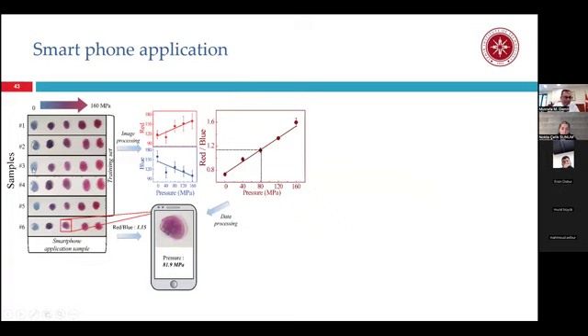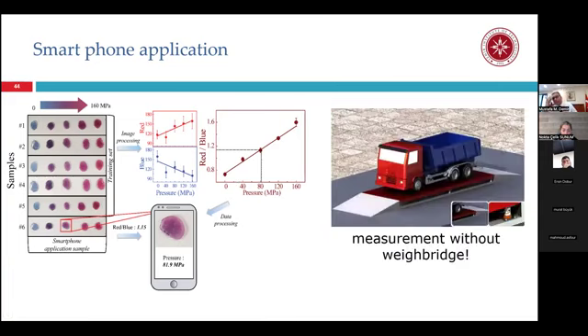So we have seen 6 different samples, originally prepared blue. Then we apply force, and the same set of experiments, you see reproducibility of the material. You apply force, then the blue color turns into a remarkable red, and one can write an app for smart mobile phones, one can separate the color into coordinates from blue and red. You see, in our case, for increasing pressure, we succeeded to separate the blue and red color contributions. So given that, one application could be as follows.